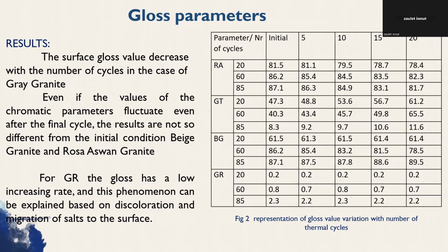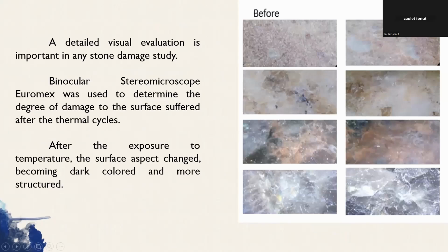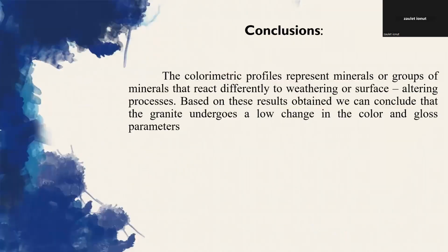For Romanian granite, the gloss is low, with an increasing rate, and this phenomenon can be explained by discoloration and migration of salt to the surface. Microscope analysis and visual evaluation are all important for damage study. After exposure to temperature, the surface aspect changed, becoming darker, colored, and more structured. And in conclusion, the colorimetric profiles represent minerals and groups of minerals that react differently to weathering or surface altering